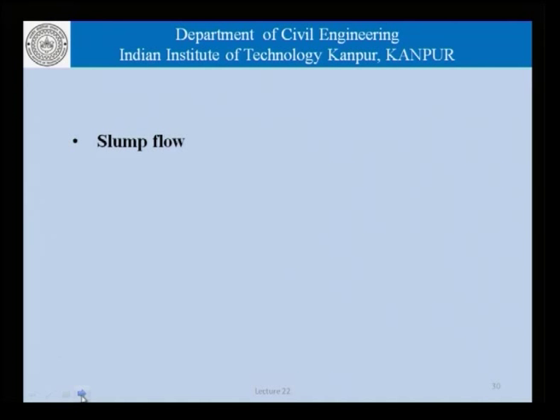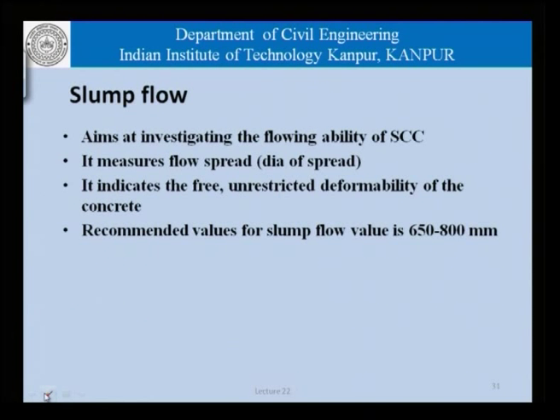Coming to the slump flow, the test aims at investigating flowing ability of the self-compacting concrete and measures the spread, the diameter of the slump being a measure of that flowability, and indicates the free unrestricted deformability of the concrete. Recommended values of slump flow are in the range of 650 to 800 millimeters.